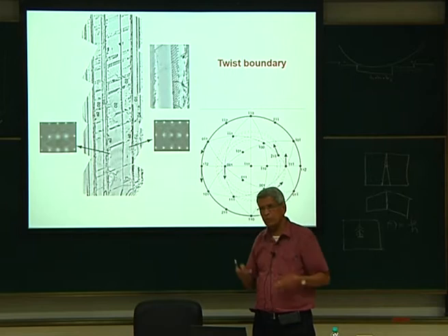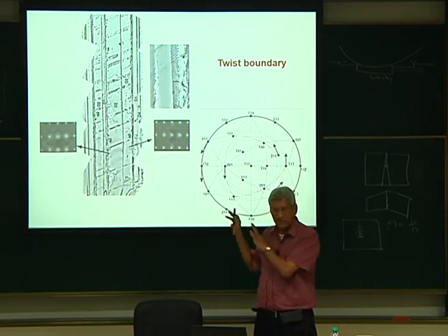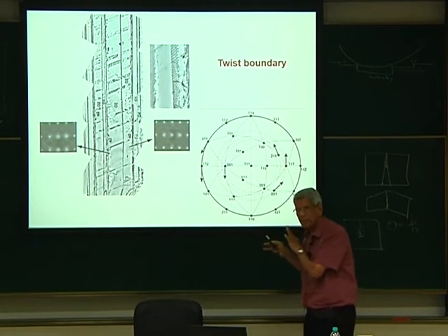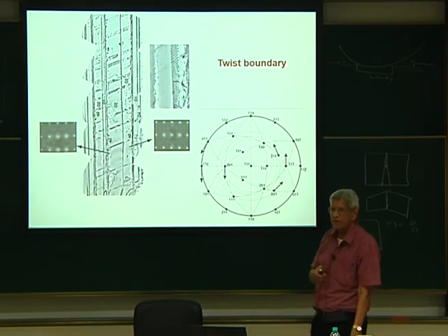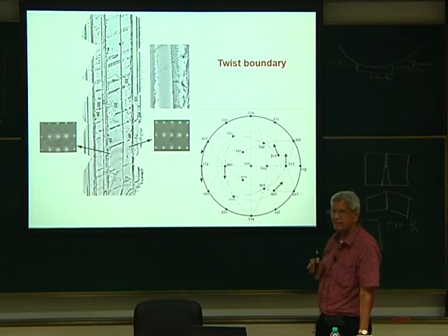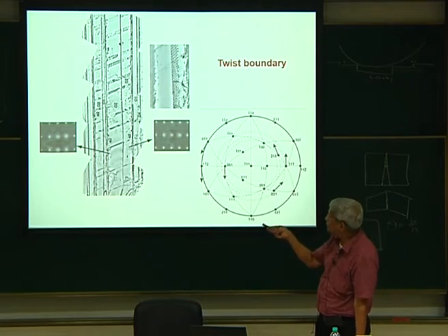Okay. Like the Kikuchi bands you see in EBSD, exactly the same type of band you can see here. They will be very faint, and one property in a microscope is that these Kikuchi bands are very sensitive to tilt of the sample because the origin of the Kikuchi band is within the sample itself. The sensitivity is less than 0.25 degree. Because of that, using this shift, I can immediately find out the shift from this region to another region.